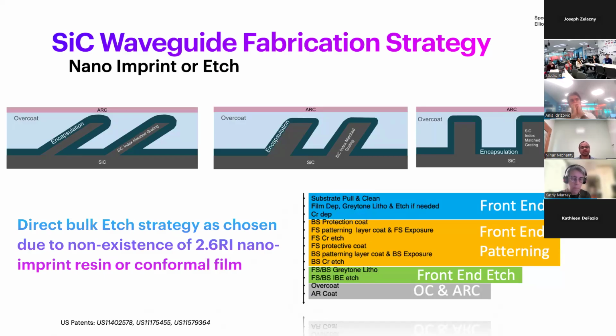on silicon carbide. We followed a standard semiconductor-style fabrication flow that is similar to a far back-end of line logic metal layers with films, lithography, etch, and encapsulation blocks. For people who are not from the semiconductor industry, a typical, let's say, iPhone chip has about 12 of those metal layers in each chip.